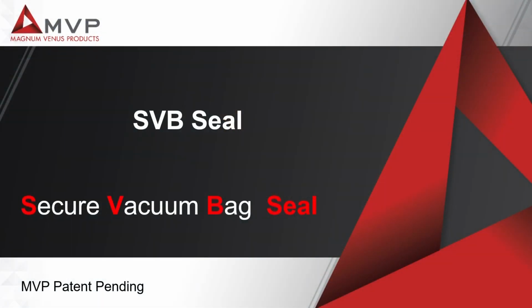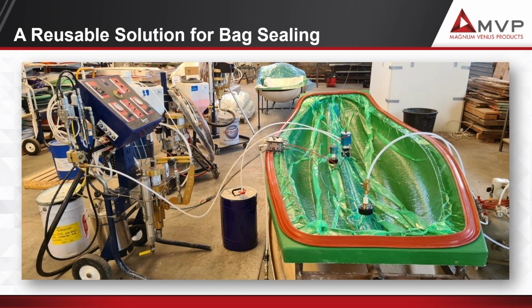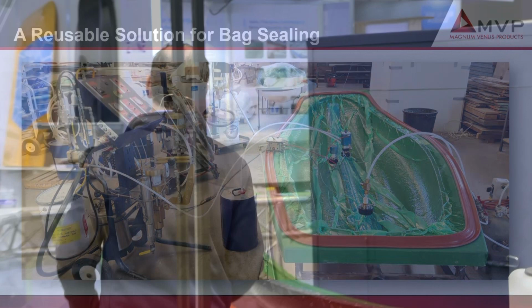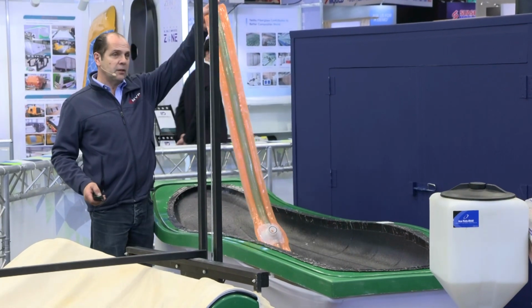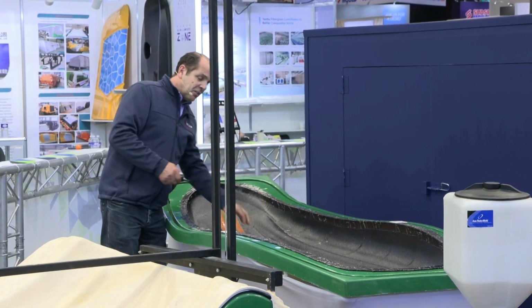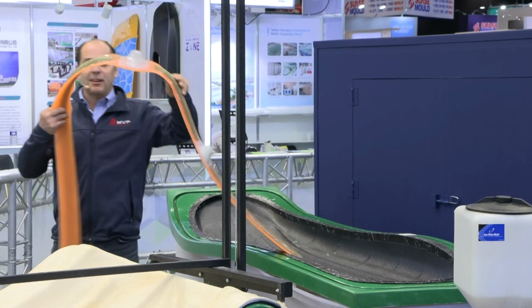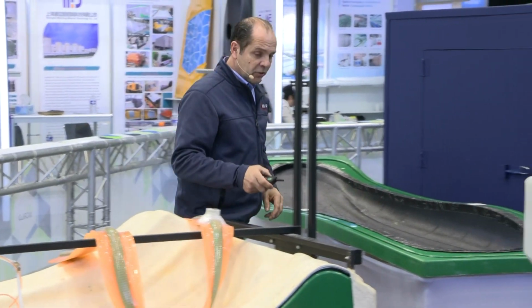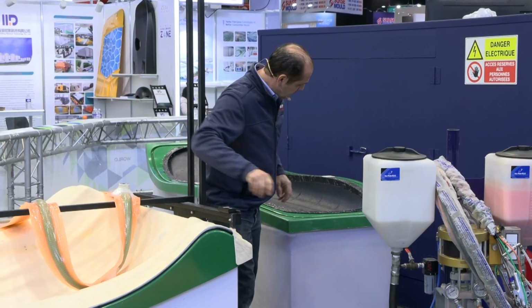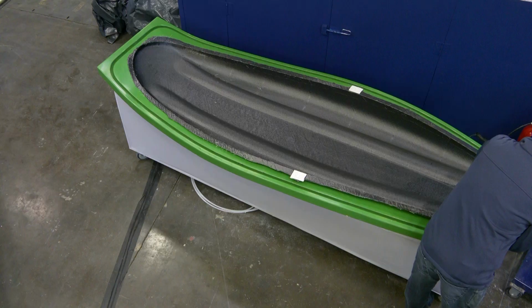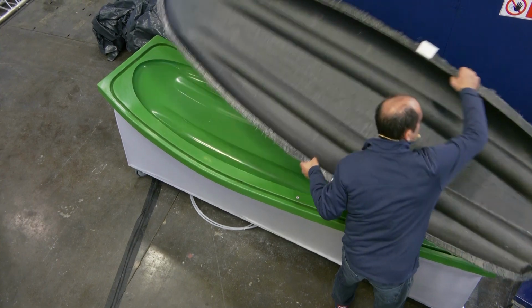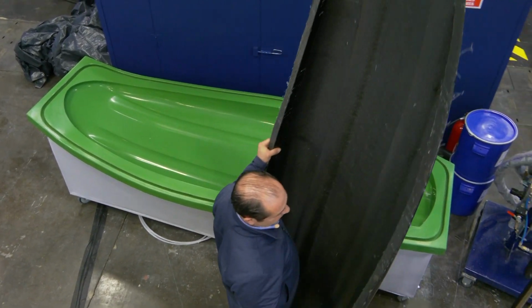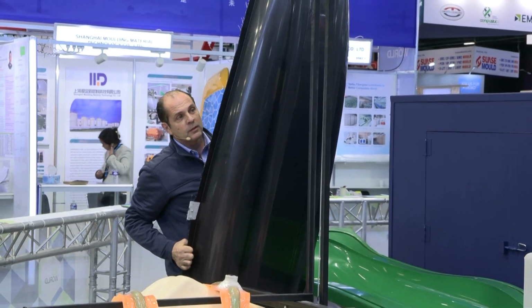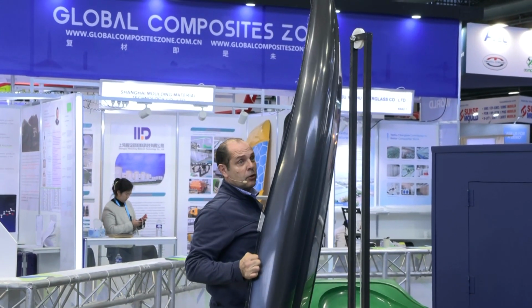Then we have shown this week also the SVB seal, when you use a part with a plastic bag. Then we show how to seal a plastic bag without tacky tape. So the part we have done together is the part which is here, where we use the collapsible resin channel in the center, with the plastic bag on the top, that we seal with the SVB seal. And then we inject it. And when injecting the part, I demolded the part this morning. We get that part. No air bubble, everything under control.